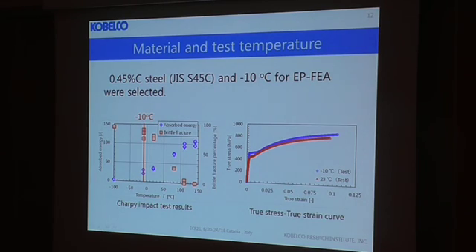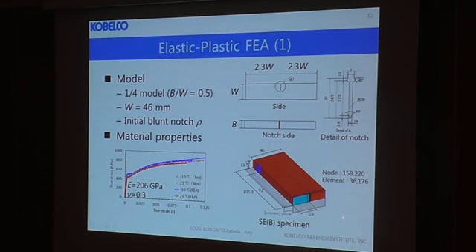0.45% carbon steel, JIS S45C, was selected for examination. Charpy impact test results and the true stress true strain curve obtained from tensile test are shown in these figures. From the Charpy impact test results, -10 centigrade was selected for EPFEA. FEA model and material properties are shown on this page. An SE(B) specimen with a rectangular cross-section of width W equal to 46 mm was considered for examination.